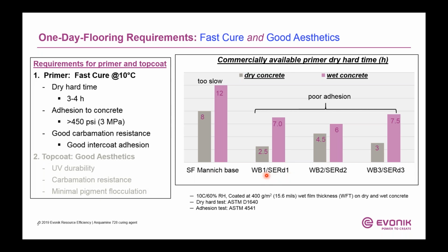But for the waterborne system, we looked at 3 known fast cure systems, and they are all with solid resin dispersion. SRD stands for solid resin dispersions. We evaluated all these three systems, and all these systems were evaluated at 10 C.